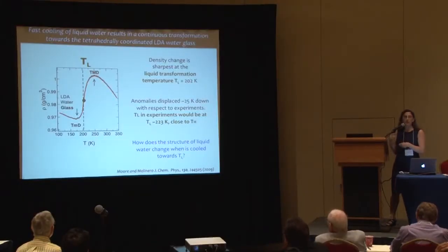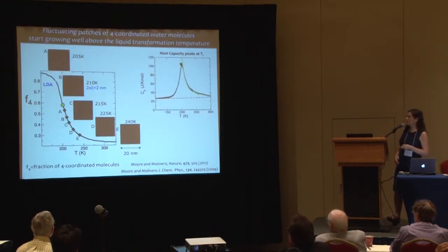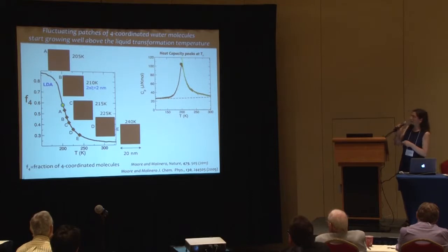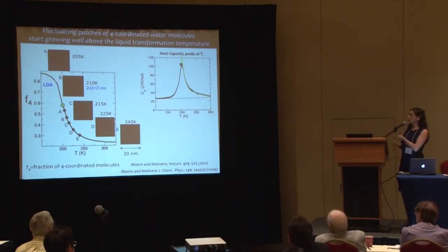What's going on with the density going up and then down so fast on cooling? I'm showing the fraction of molecules in the liquid that have only four neighbors — the signature of the glass. In snapshots of a very large simulation — over a quarter million molecules, 20 nanometers, huge for us — as you approach the point of maximum change in four-coordinated fraction, you see more and more blue. The blue domains are highly correlated and become larger: not a random development, but large patches developing on cooling. This is the birthplace of ice, associated with a heat capacity increase fitting the same power law as experiments.